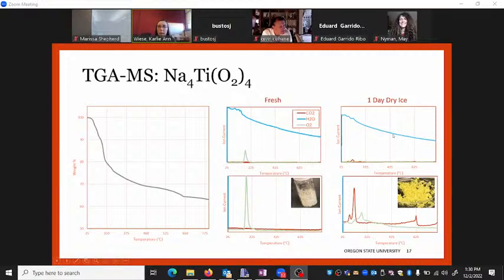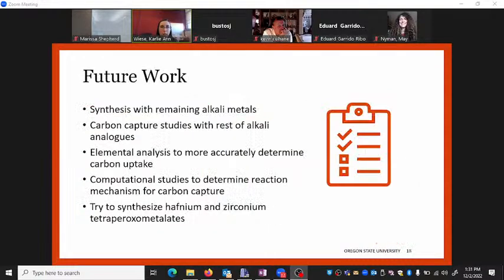When we run the same thing with the 1 day dry ice sample, we now see that there are peaks for CO2 in addition to oxygen. So definitely CO2 in some way has combined into our material. So that's where I'm at with my research now. Still have some more work to do on it.